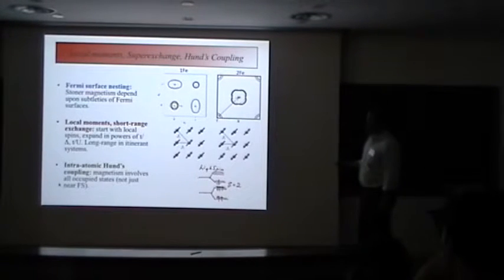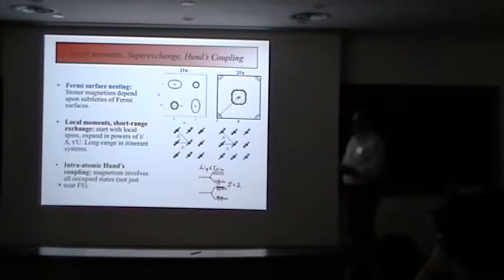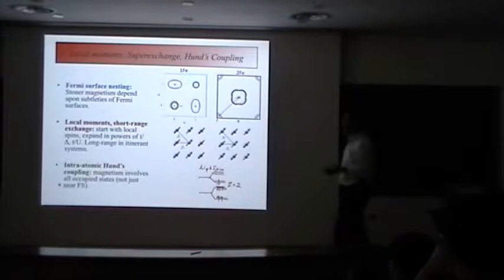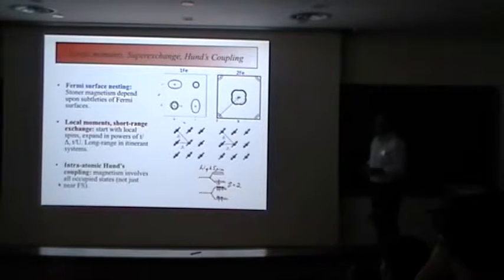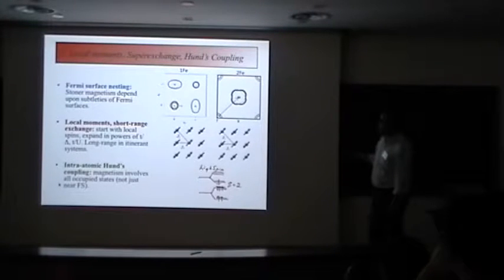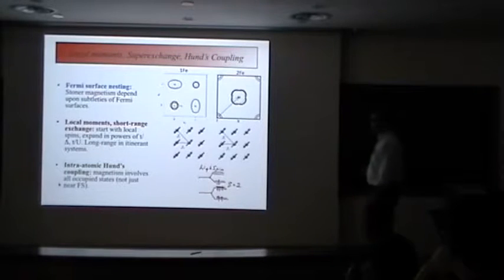So there, what you'd expect is that magnetism is really going to be governed by subtleties of the Fermi surface itself, and orbital content could be playing a role there, because the orbital content changes going around the electron pockets and also going around the hole pockets.